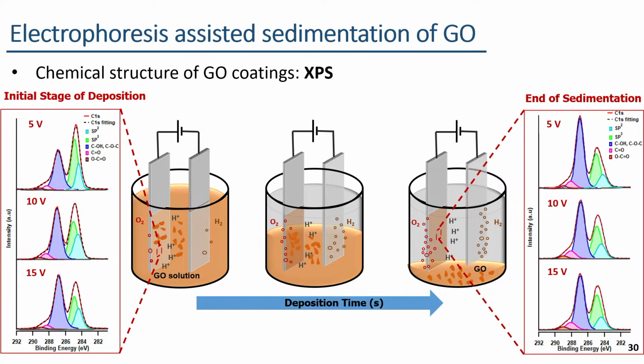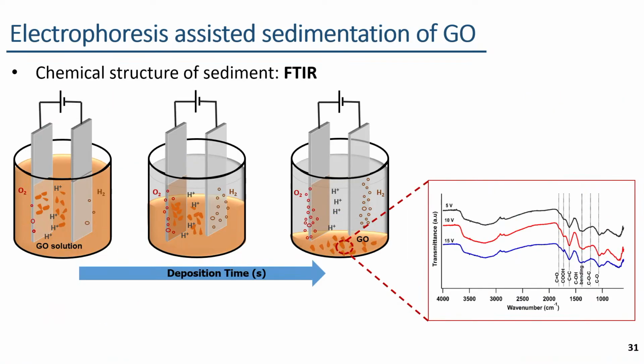So, here this variation in the amounts of basal plane oxygen functionalities in these coatings is due to the size selective deposition of graphene oxide, which is influenced by the sedimentation process. Then comes the chemical structure of these sediments separated under different EPD potentials.